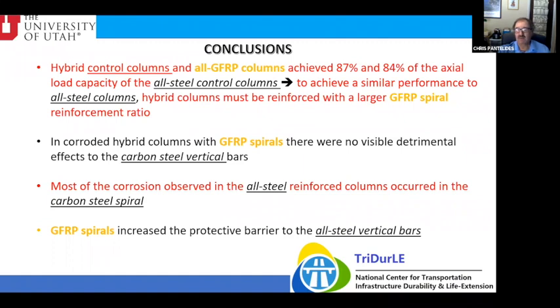This is an important conclusion because all steel has a little bit less tensile capacity than fiberglass. On the other hand, fiberglass is very brittle, I mean, less than 2% strain. So this kind of result makes sense. Also, as I mentioned, because the spiral has a very low modulus of elasticity, about 1/5 that of black steel, you need to put more material, a bigger spiral, to achieve the same capacity as you do with the all steel columns. Of course, another thing you can do is also reduce the pitch, the spacing between the hoops.